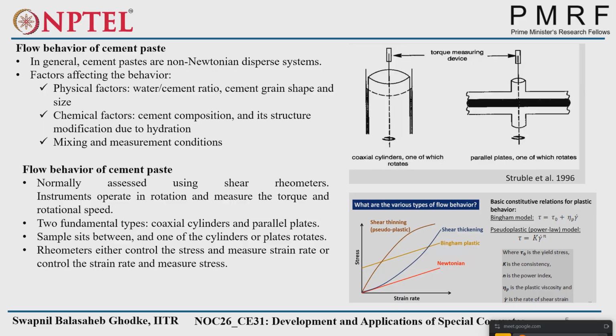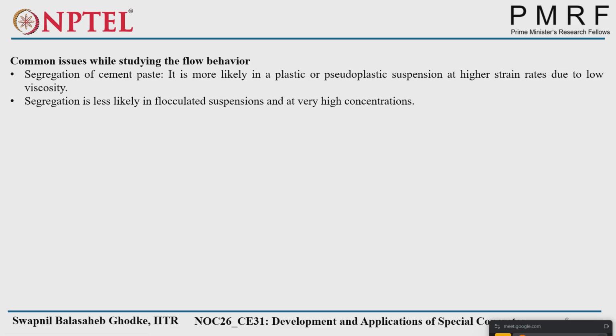Then another model is the power law model, that is tau is equal to k into gamma dot raised to n. n is called the flow index. That is like a fitting model. If you fit this model, you will get the n value, the fitting coefficient or flow index. So tau zero is the yield stress, k is the consistency, n is the power index, eta p is the plastic viscosity, and gamma dot is the rate of shear strain. Okay. Does anyone have any doubt up to this? Okay, no doubt, I think.